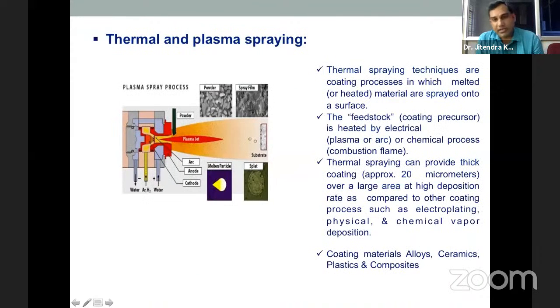Another kind of improvement is thermal spray coating or plasma spray. You have inert gases that generate the plasma, and you can feed powder into that plasma. Because of its high kinetic energy, the powder goes to the substrate and can diffuse into the surface of this material, and you can make a coating. You can generate this by thermal spray coating at approximately 20 micrometers, and you can coat alloys, ceramics, plastics and composites over the surface by using these methods.